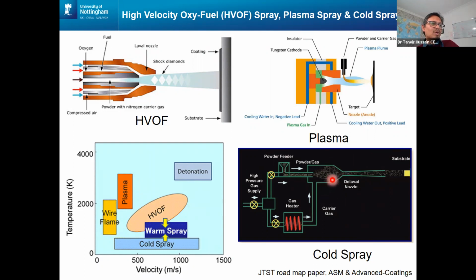Here, we have got a de Laval nozzle, or a convergent-divergent nozzle, where we're injecting powder particles. No heat is coming in, and that's the reason it's called cold spray: we're not melting anything here. These particles are then hitting the substrate, deforming at a high strain rate. So we are talking about strain rates of 10 to the power 6 to 10 to the power 9 per second. And that then forms a coating, and that can also be used for additive manufacturing or net shape manufacturing.